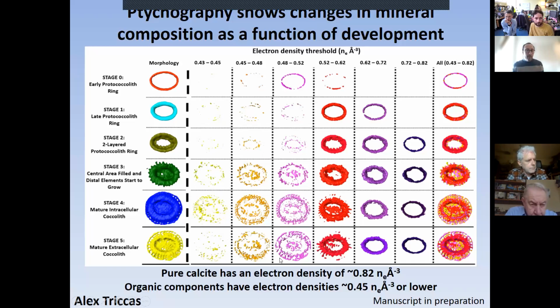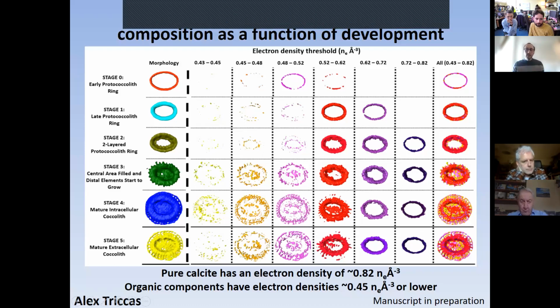And of course, that is going to be a mixture of occluded polysaccharide and the coating of the polysaccharide on the surface. We're talking about structures that are a few tens of nanometers in thickness. So that is very much what's happening here. What is happening on the inside is a different matter, because here the coating of the polysaccharide is on the outside of the coccolith, and that is far enough away from the core of the coccolith to cause this decrease in electron density that we see here more in the center. So it cannot explain what we see there. So it has to be something else in there. That's all I can comment on.